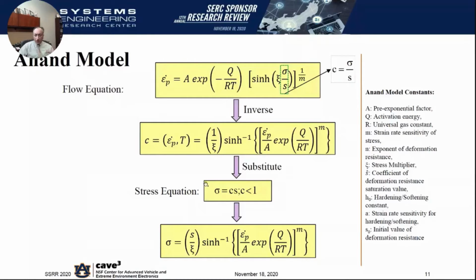So most of us are familiar with Hooke's law. Stress is directly proportional to strain in Hooke's law, and we generally use something called the elastic modulus. But because this is a nonlinear material, we are going to start off with a stress equation that looks like a pseudo Hooke's law, sigma is equal to Cs, where C here, instead of being the elastic modulus, is a parameter that depends on strain rate and temperature. So you can see the form of C here. S, instead of being strain, is an internal variable that represents the deformation resistance of the material. And so if one takes the form for C and plugs this into this equation, one can formulate the equation for stress as a function of strain rate, temperature, and the internal deformation resistance.